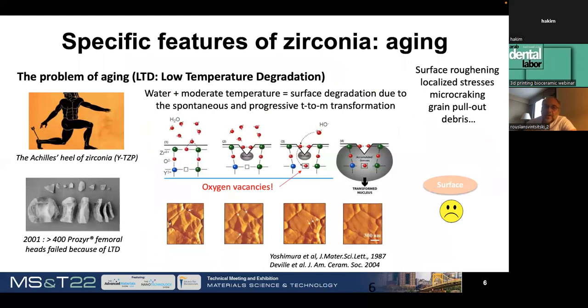Here you have this low temperature degradation explanation. It acts on the structure itself of the material, and you can see in the bottom left corner of the picture, the picture of the orthopedic femoral heads, the failure, which was noticed in 2001, and which was caused by this low temperature degradation. So the roughness of the surface of the part is degrading, and it brings total damage of the implant, which is not good for the human body, of course. When you have some cracks, when you don't have a reliable structure, you cannot implant these kinds of parts.